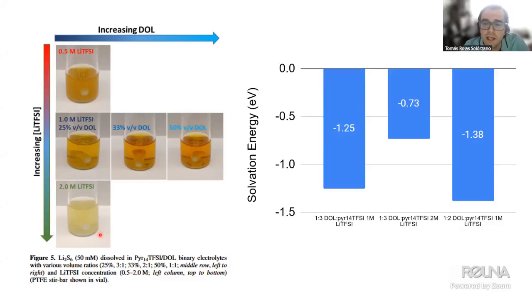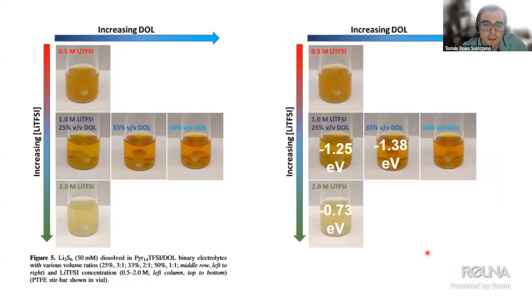And what we found is that the energies we predicted, which again is related to how strongly the polysulfide attaches or interacts with the rest of the electrolyte, and relates to its solubility, related very well with the color of the solution and with the solubility of the polysulfide. Increasing the DOL in this case gave a relatively smaller change in the solubility, whereas increasing the TFSI, the other component of the electrolyte, gave a much more significant change in the solubility of the polysulfide.